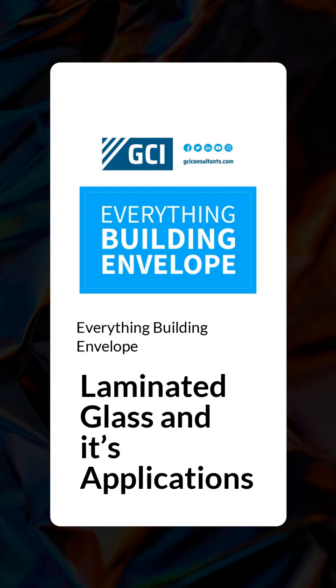It's the interlayer that has to be tested with a specific framing system. So what they'll do is they'll build a mock-up of this, and it's also going to be size dependent. So you'll have a given size. I know in the commercial size of things, most people test up to about a 40 square foot piece of glass. So let's say we have our 5x8 test specimen. It's either going to be insulated laminated or just laminated glass.